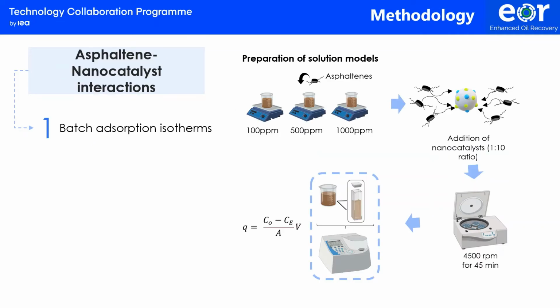The nanoparticles' absorption capacity for asphaltenes was studied by batch experiments. A stock solution containing 2000 parts per million of asphaltenes was diluted to obtain solutions with different concentrations between 100 and 2000 parts per million. Nanoparticles were added in a 10:1 ratio of adsorbent mass to solution volume, and the mixtures were stirred at 300 revolutions per minute for 24 hours. The nanoparticles containing asphaltenes were separated by centrifugation, and the supernatant was analyzed in a UV-based spectrophotometer.